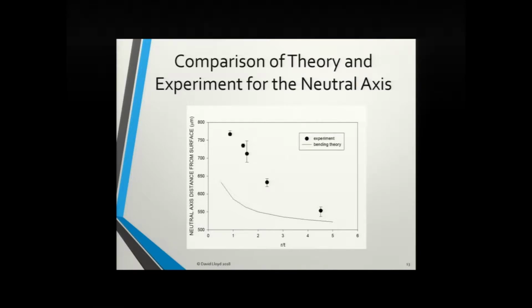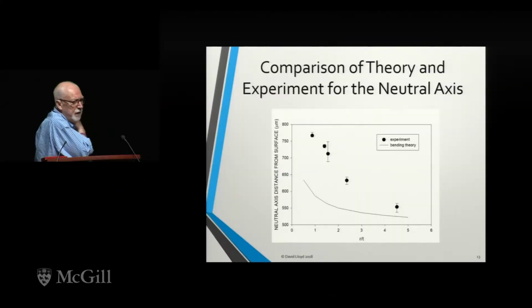So the theory underestimates quite significantly the level of neutral axis motion. And that's pretty well consistent with the 6000 series alloys that we've looked at: 6016, 6010, 6111. They all show this fairly large difference between what the theory is telling you and what the actual degree of bending is telling you. This is not surprising when you look at how the analysis was done. I'm not going to go into how the basic mechanics analysis was done, but it's a fairly consistent trend that you get.